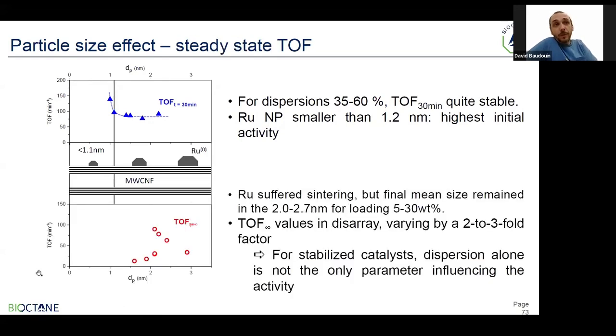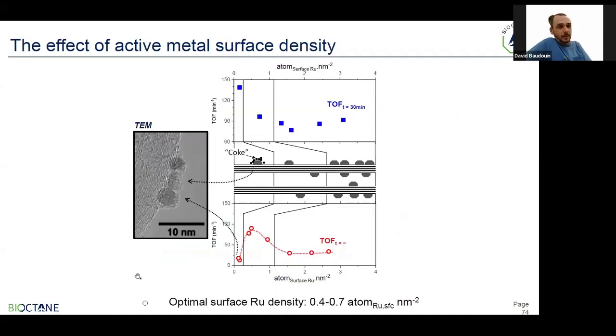Now, the catalysts suffer, however, from deactivation, or very, very early deactivation, and then the catalyst finds some stable activity. And here is reported in red the turnover frequency after stabilization. This, of course, is plotted against the dispersion of the metal after the test. And you can see that there is not much correlation observable anymore, with particles at 2 nanometer having very different turnover frequency. Next slide, please.